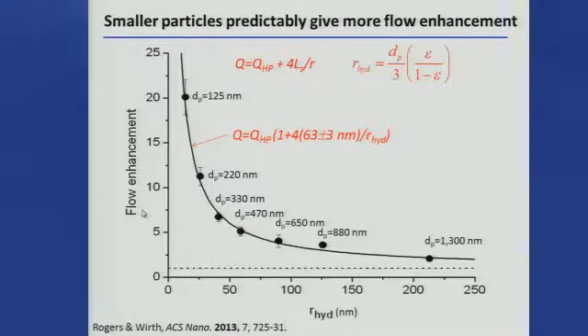Okay, yeah, right. So what I did here, there's a lot of data on this, and I went through this kind of fast. So this is a plot. Let's look at the equation first. So this is the flow rate. If I take Q over Q Hagen-Poiseuille, I'm going to get my flow enhancement. So this is the ratio of Q over QHP. And it's fitting to 1 + 4 slip length over the hydrodynamic radius. And so I need to plot this versus hydrodynamic radius. I get that from the particle size. Now, I could do as you were suggesting, which is just plot it versus particle size. The only reason we couldn't do that is because different particle sizes give us different porosities. We get the lowest porosity just for these two things on the end, and then the other ones tend to give us higher porosities. So I had to include that because that actually changes what the effective hydrodynamic radius is.